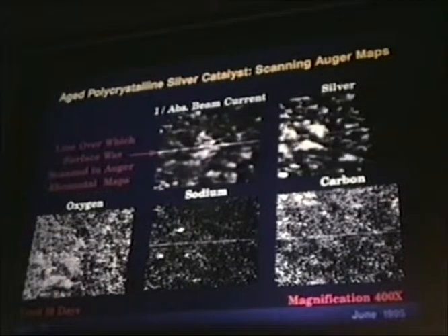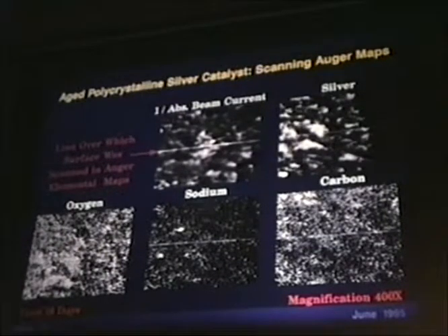Indeed, in the sodium map, at least three of those spots, as best as we could resolve these from our old report, they're very intense, several hundred angstrom to 1,000 angstrom size sodium aggregate particles. At that point, then, we indeed zeroed in on these bright sodium particles, and by Auger analysis, convinced ourselves that they were entirely rich in sodium. This work with the pure polycrystalline silver promoted by sodium points to promoter aggregation as the dominant mechanism for selectivity aging when aged in the absence of gas phase chloride promoter.